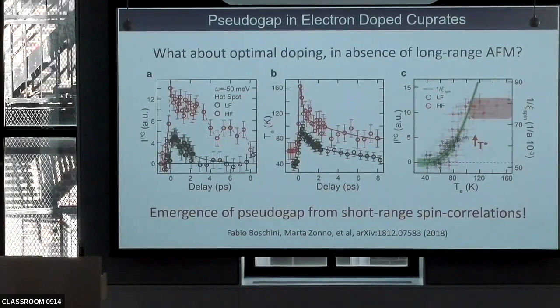What you're seeing here is two different fluence regimes. Red is high fluence, black is low fluence. The horizontal axis is delay, and the vertical axis is the intensity in the hotspot. So it's the spectral intensity in the hotspot. If I didn't have a pseudogap, intensity would be 1, and if the gap is a complete suppression, intensity would be 0. Any value in between is the evolution of a gap which is not complete.